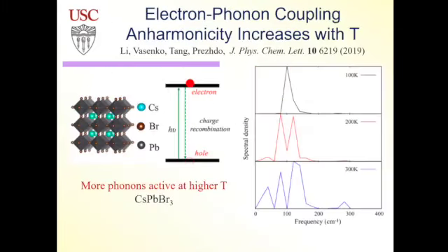But to conclude on perovskites, they're very anharmonic materials. So when people make simple models, assuming harmonic vibrations, phonons, these are not phonons. You have very low frequency vibrations, and the system is very anharmonic. So if you raise temperature and look at the electron vibrational coupling, at low temperature you have some dominant phonon, but if you increase temperature, you have more and more vibrations contributing to electron vibrational coupling, because the system is very anharmonic. And the types of calculations we do, atomistic calculations, become important, because simple harmonic models that many people use don't apply.